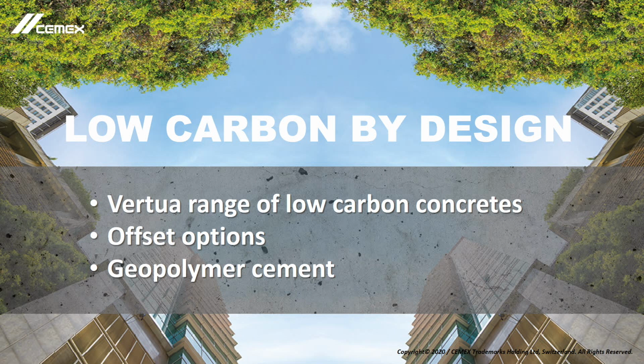Yes, again, thank you for the question. So regarding the properties, every time is different. Even if you have normal concrete and you change the aggregates or the sand, or you have high performance, every time the properties are different. If you are talking about the stress strain models, and if we have to create new models for geopolymer concrete, the concept is the same as the one we follow for conventional OPC. Overall, the behavior is pretty much the same. Clearly, depending on the mix, you get different strengths, but the behavior is pretty much the same: good compressive strength, weak tensile strength, brittle in tension. It's pretty much the same also for the Young's modulus with the conventional concrete. So we should treat this as normal OPC.